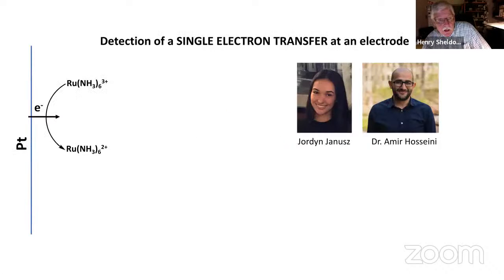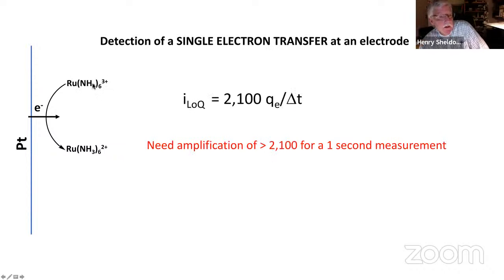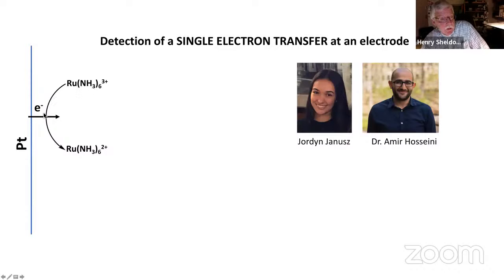Okay, here's the second short story. Single electron transfer at an electrode electrolyte interface. All right, this one's tricky. So I pointed out before, you can't measure a current associated with a single electron transfer. What you'd like to do, the ultimate measurement I think in single particle counting, is you have one molecule, in this case ruthenium hexamine, and it gets reduced at an electrode surface to the 2+. This is a fast outer sphere reaction. There's one electron transferred. Can you measure that? For one molecule, one electron for one molecule.